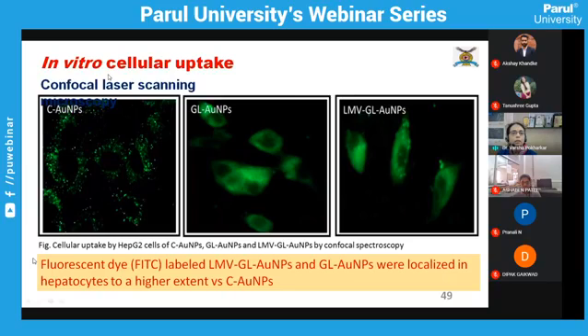The in vitro cellular uptake studies were done using confocal laser scanning microscopy. And here what we have done, we have labeled the gold nanoparticles with a fluorescent dye, that is FITC. So the leftmost picture is of the citrate reduced gold nanoparticles. The middle one represents the glycyrrhizin reduced gold nanoparticle, and the rightmost represents the lamivudine capped onto the glycyrrhizin gold nanoparticle.